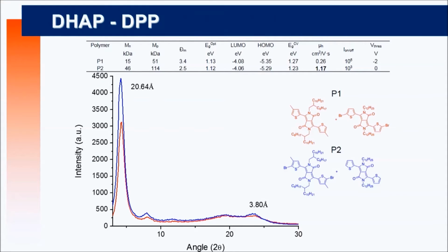However, we think that if you put a bromo group here, this is an electron withdrawing moiety, it will activate or make this CH bond more acidic. If you put the bromo group here, but you block this beta position with an alkyl side chain, selectivity is good here, selectivity is good here, and you make the coupling in the right position. If you do the opposite here, we think you have some cross-linking here. So that's still a limitation. We're not sure. Perhaps it's a problem of selectivity and finding the right ligands and the right catalysts, but it's a limitation.